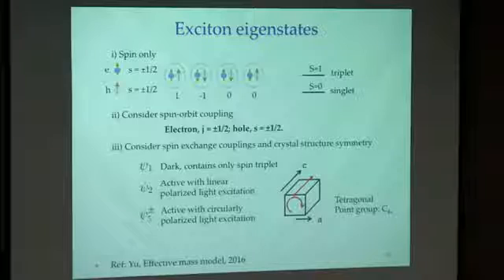And further, we consider the spin exchange coupling between the electron and hole, and also the crystal structure symmetry. We consider the tetragonal phase here, and it has a point group of C4v. Based on the symmetry of the conduction and valence bands, and also the crystal symmetry, we can figure out that those 4 states are the eigenstates, where Psi 1 is dark, not optically active. Psi 2 is active with linearly polarized light excitation along the c-axis of the crystal. And Psi 3 plus and minus are active with circularly polarized light excitation in the ab plane.